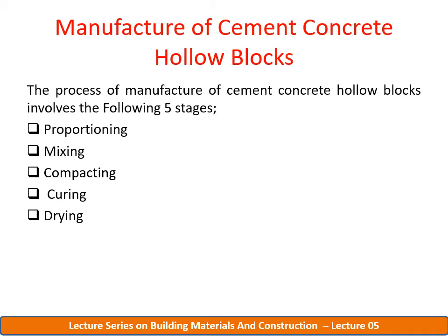Hollow blocks are stacked with their cavities horizontal to facilitate through passage of air. A period of 7 to 15 days of drying will bring the block to the desired degree of dryness to complete their initial shrinkage. After this, the blocks are ready for use in the construction work.